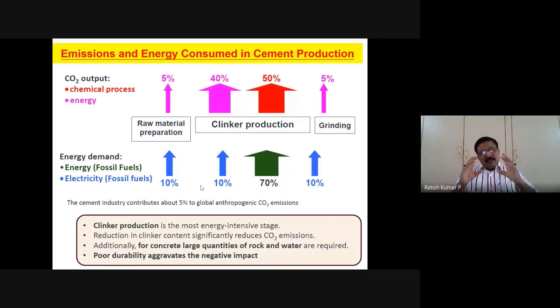When you compare the raw material preparation and then go for clinker production, as everybody knows, in the rotary kiln the argillaceous and calcareous materials are burnt at a high temperature, and what comes out of the rotary kiln is called clinker. Then you quench it, take it to the ball mills, add certain performance additives along with the gypsum, and then you get the final finished product. So there are several stages involved.